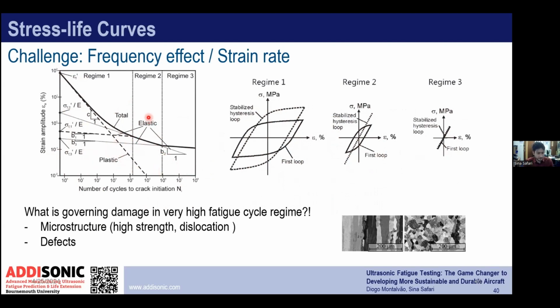So this graph here shows 3 regimes. Regime 1, which is low cycle fatigue, and as you can see in regime 1 we have elastoplastic behavior, and we can say there is dominant plasticity there. In the second regime, where we have a transition between low to high cycle regime, we have a little bit of plasticity involved in the macrostructure. And in the third regime, which is the very high cycle fatigue regime, the system is almost linear.